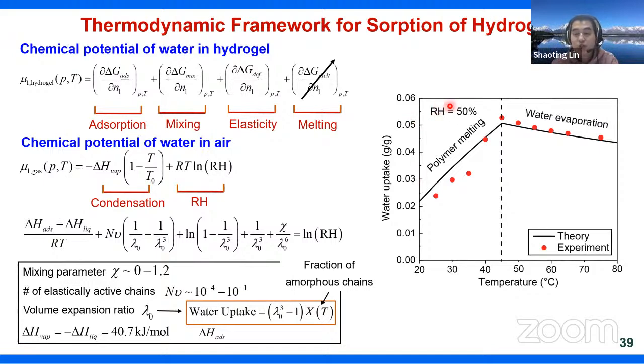Here we control the humidity at 50%. The red dots are the experimentally measured data, and the black curve is the theoretical calculation. What we can find is that at a relatively low temperature, we indeed observe enhanced sorption capacity as the temperature increases. However, when the temperature increases further, the sorption capacity decreases accordingly. That is because when you further increase the temperature, dehydration eventually dominates.